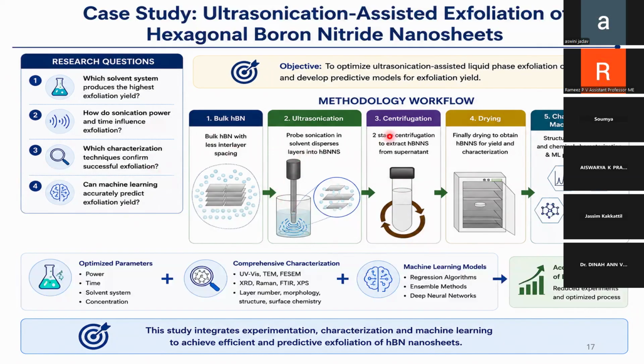So this was the methodology workflow I had, where bulk hBN was taken into the solvent and ultrasonicated. And after ultrasonication, I had centrifugation twice, actually, at lower RPM and higher RPM. And then I dried it and then found out the yield percentage. As I said, yield percentage is nothing but you have an initial weight, and then after doing these steps of ultrasonication and centrifugation, you will be getting the hBNNS and take the weight of it, and the fraction of final by initial will give you the yield percentage.